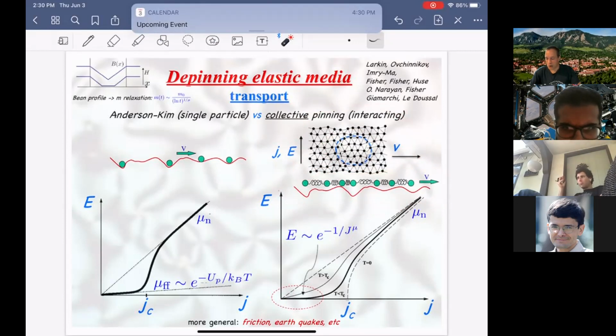It can always move non-linearly, but it has an IV characteristic that is strictly non-linear, namely has no linear response coefficient, and therefore resistivity is actually strictly zero at low temperatures and low current. So this thing is strictly nonlinear. Of course, at large currents, it crosses over at finite temperature to a flux flow resistivity where it does have linear normal state-like IV characteristics.